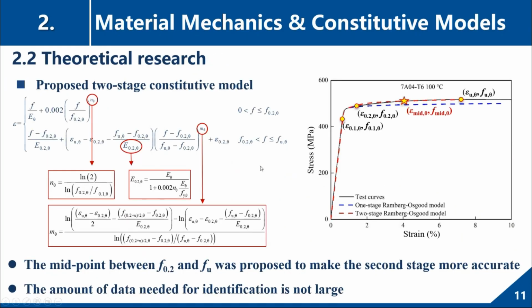Based on the material test results, as well as the results collected from literature, we proposed a two-stage constitutive model. Actually, this model is for high temperature material property, and it is based on the ambient temperature two-stage constitutive model, proposed by Xiang and me, and published in Journal of Structural Engineering in 2021. And it is really a highly cited paper. Till now, I think the citation of it is around 150.